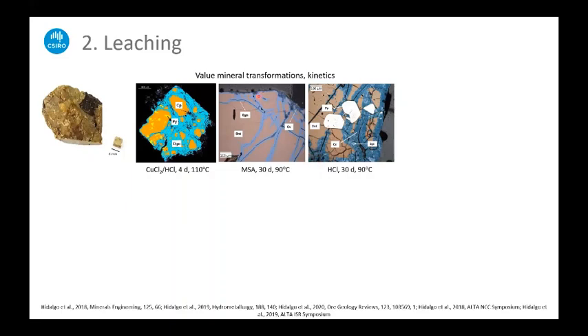And you can see in this image, what's very interesting is that the fluid moves along the fractures and the cracks. And in this case, for the hydrochloric acid, you can see that the rate of leaching was higher for the same period of time because more of the bornite in this case was converted to digenite.